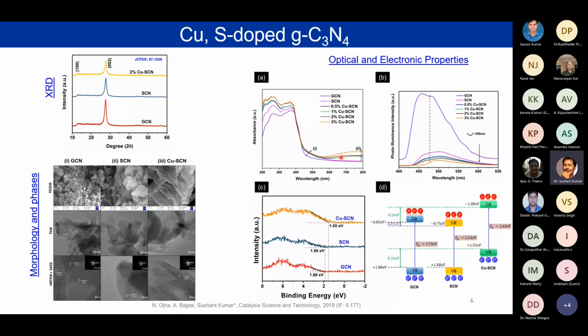Now here you see the photoluminescence intensity. As I told you, the electron and hole recombine and they are lost. If we see a more intense peak, it would mean that there are more such events, and hence a more intense peak is not good for us. We need a very low intensity peak, which would tell us that the electrons and holes are reaching the surface relatively more. This was true for graphitic carbon nitride, whose function is limited by the recombination events.